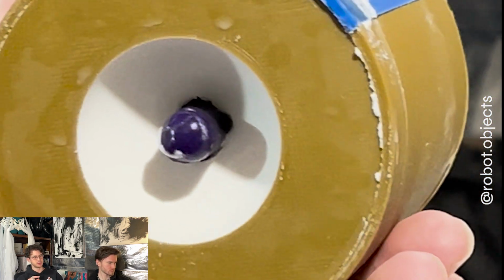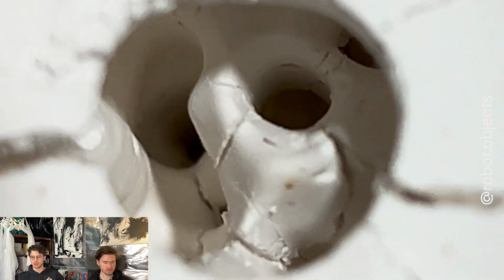And we did that whole method in particular to then transfer over to those metal collars, which was an interesting process. It was kind of like an extra step, but it didn't work as well as just doing it in a solid form metal. It should be in the same mold the entire time. That's what you get when you don't put it in the same mold the entire time. You get all that cracking.